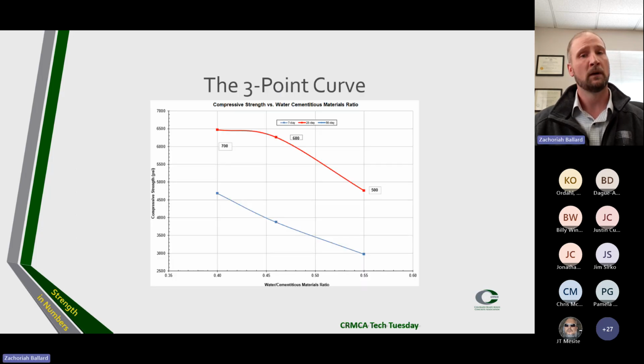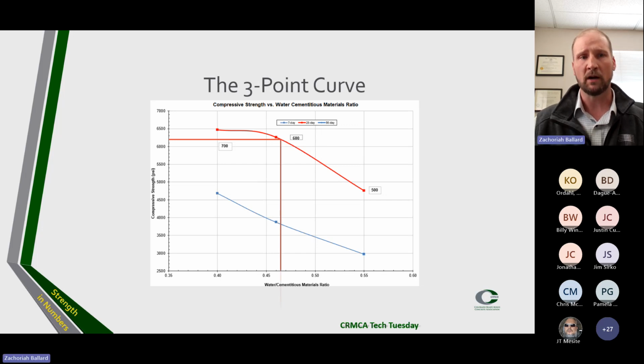Shown here, using a 3-point curve, we can then pull out a design water cement ratio and interpolate the mixture proportions for our design mix. That looks like as we come across from our design strength till we hit our strength curve, drop that down to our water cement ratio at the bottom, and we can interpolate our values for a design mix.